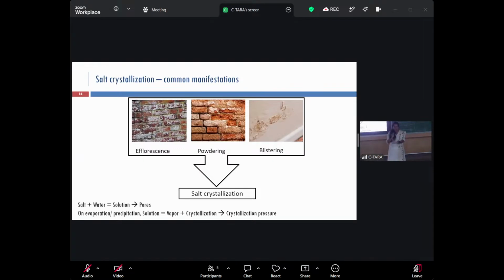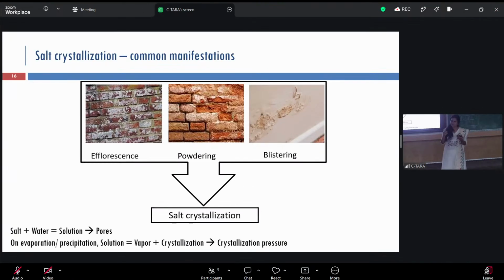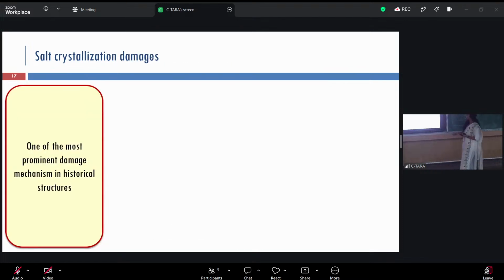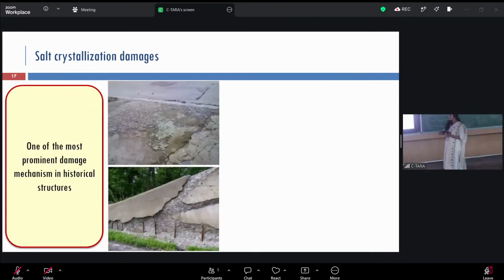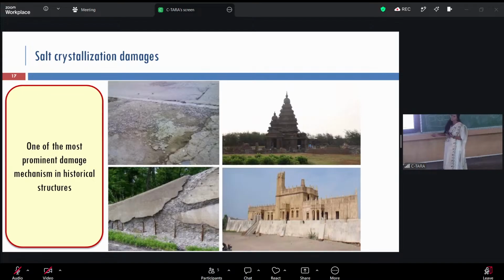If this precipitation happened inside your material, if the evaporation rate was higher, that is going to damage your material. That again will build up stresses. The salt will not have space to grow inside. Material will crack. That is salt crystallization. And because of that, it is known as one of the most damaging materials, not only for heritage structures, any structures which are exposed in these conditions.